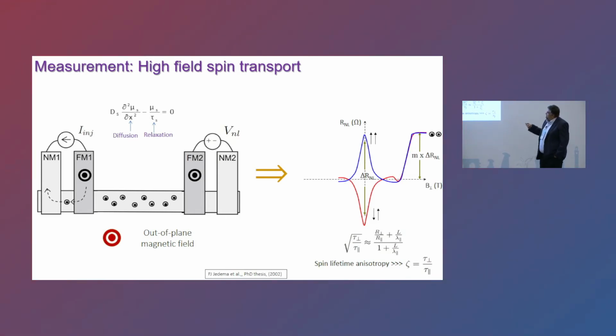This is the Hanle spin precession measurement that I mentioned at the low field regime. Whenever you are forcing these ferromagnets to be out of plane, you are forcing the spins in your channel to be out of plane. By comparing the magnitude of this signal and this signal, you can get an idea about the spin anisotropy, meaning what the spin lifetimes are for spins pointing out of plane versus spins pointing in plane.